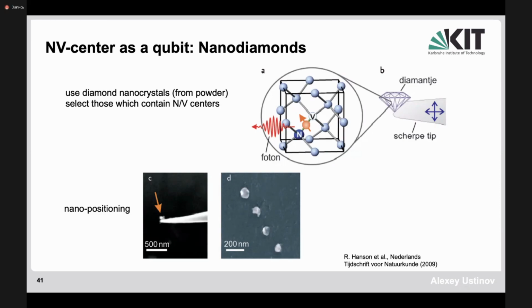And clearly, since you can detect the emission of light optically, you can measure very local magnetic fields very precisely, because the fine splitting between the spin states of an electron at the NV center will depend on the local magnetic field. And therefore, you could apply microwaves, scan the microwave frequency, and then basically measure the optical response. This offers an opportunity, for example, of measuring very local magnetic fields for very tiny objects.